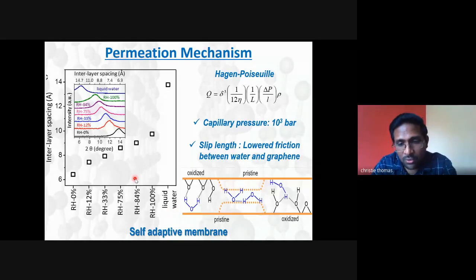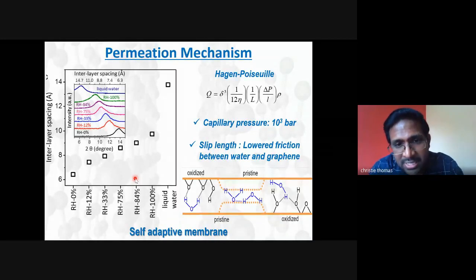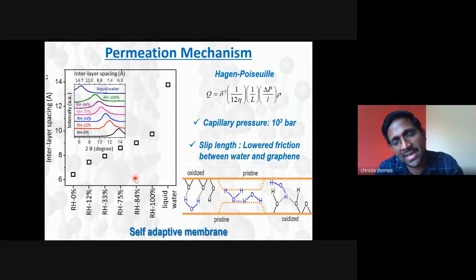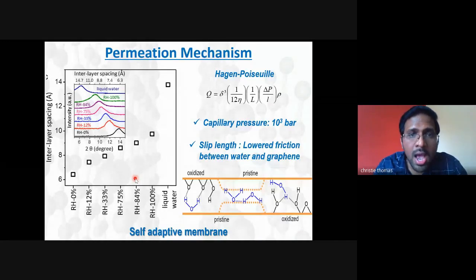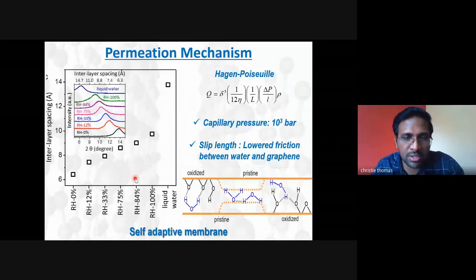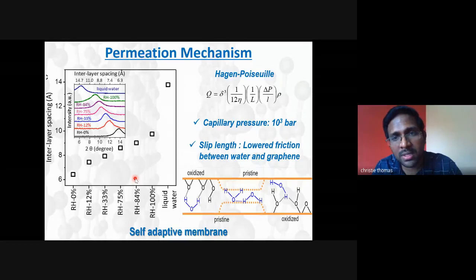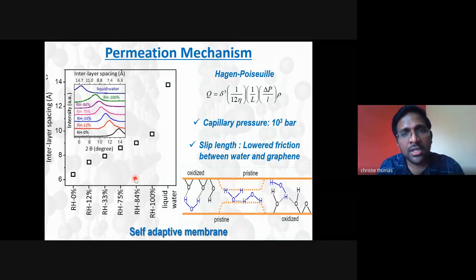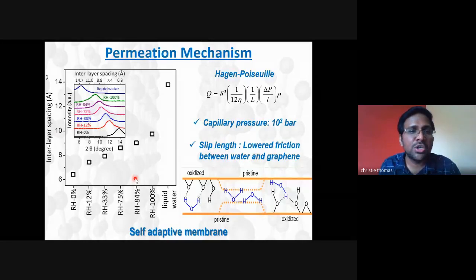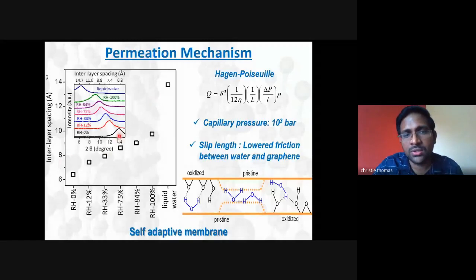So the flow rate is controlled by the interlayer distance, and the molecular permeation plays a crucial role. You can also see that the d-spacing is RH dependent, which means it depends on how much water the graphene oxide can take in. Put another way, when I put graphene oxide inside liquid water, it swells and the interlayer spacing increases to 14 angstrom. That's what you see in this graph. This is basically a simple XRD experiment.